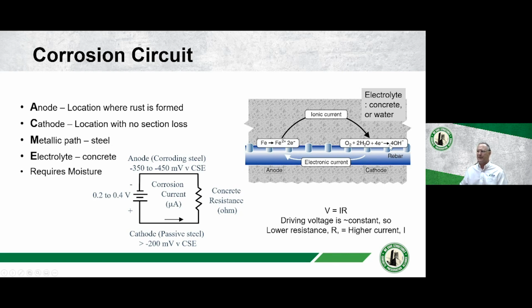When you reduce oxygen, you gain electrons, you have some water, and you create hydroxyl ion. Hydroxyl ion increases the pH in the area around the cathode. So this also sort of repels the chlorides. And then to complete the circuit, you have the ionic current that flows through the electrolyte. And that electrolyte is either concrete, soil, or water. What we do with cathodic protection design is we're really designing a corrosion protection system based on this circuit.